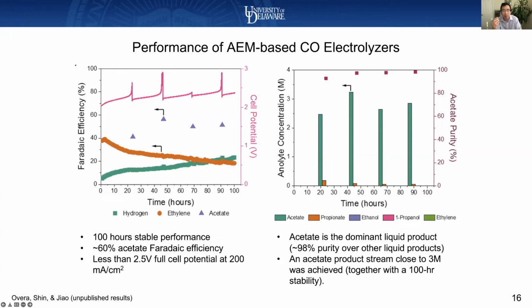And acetate selectivity actually maintained over 50% across the whole 100 hours test. And surprisingly, in the liquid product stream, we only have acetate, a little bit of propionate, but we don't have ethanol, propanol. Those are commonly observed in CO or CO2 reduction reactions. This is a kind of a surprising result.